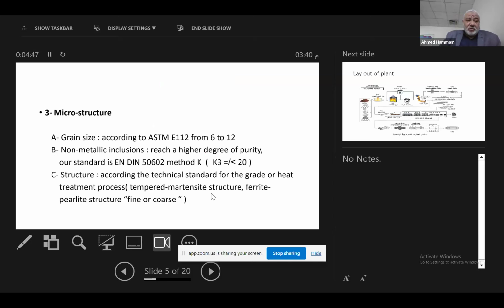The third one is the microstructure. We have to be very keen to keep the grain size and the shape of the grains in a manner that there is no distortion, and it should be according to the ASTM standard from 6 to 12. Also the grain size should be controlled according to the final application. Always you can say the final application is the master key to succeed in special steel.